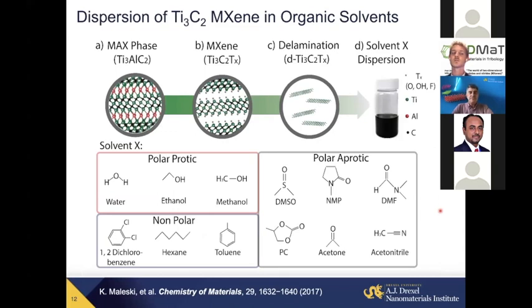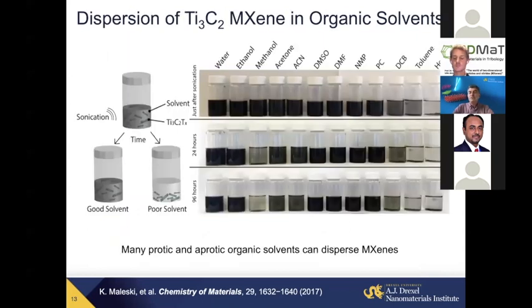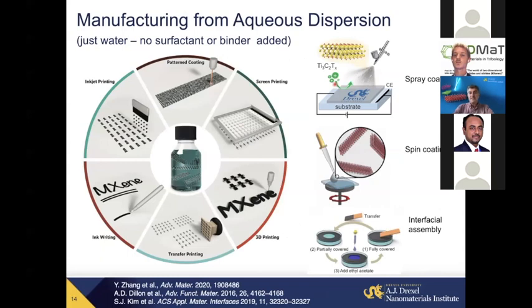Typically, we treat them dispersed in water, but it's possible also to disperse them in polar aprotic or protic solvents. For dispersion in non-polar solvents, we will have to do surface modification of this material. That's possible. This is doable if needed, for example, for dispersion in oil, but it won't happen by default intrinsically because surfaces are polarized. But what is also important is that we can use just aqueous solution, really pure water, no surfactants, no binder is needed, no toxic compounds added.